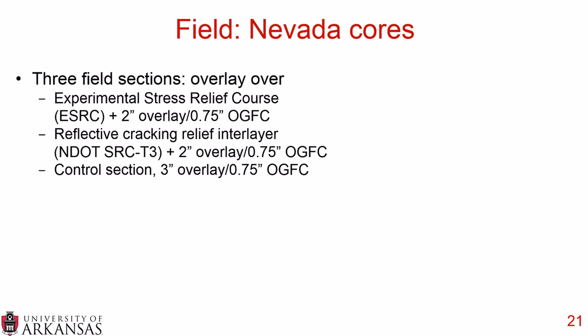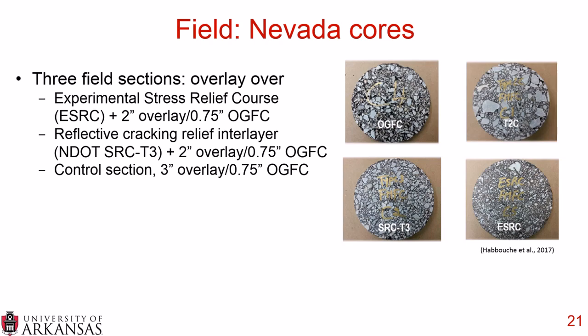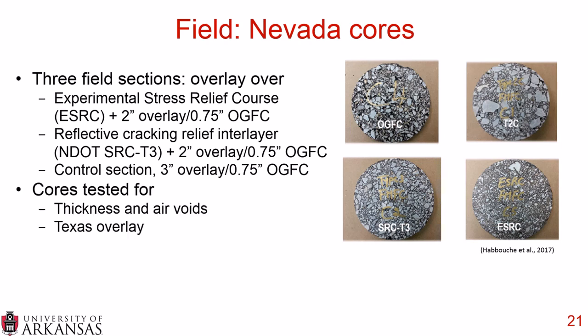So these are the 3 field sections they placed with an overlay, and then they took cores from these field sections. You can see here a picture of the OGFC, which was on all the sections, a picture of the SRC-T3, which is the Nevada DOT reflective cracking relief interlayer. They looked at the control section, the T2C, and then they looked at the ESRC. Some very nice images there of the cores that were taken. The cores were tested for thickness and air voids, and tested on the Texas overlay tester.